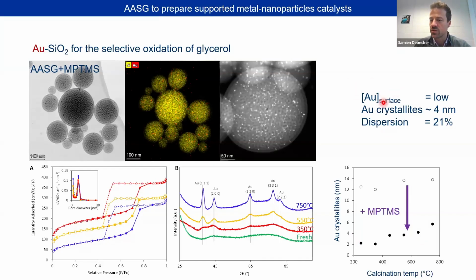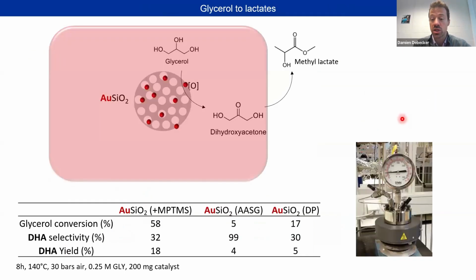In terms of gold surface, on the surface of the spheres, it's relatively low because most of this gold is inside of the spheres, but they are accessible, as you can see here, with a quite large dispersion value. And the crystallites are very small, consistent with what we see in the images. So logically, when we tested them in this reaction, we saw for the first catalyst I show you, moderate conversion, moderate selectivity, and very low yield.